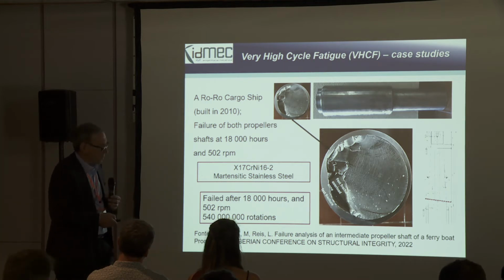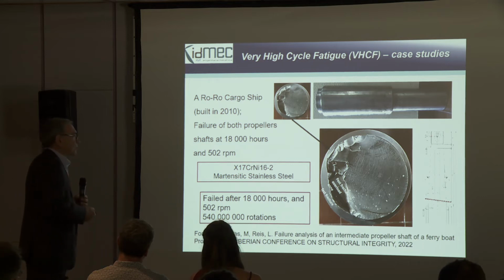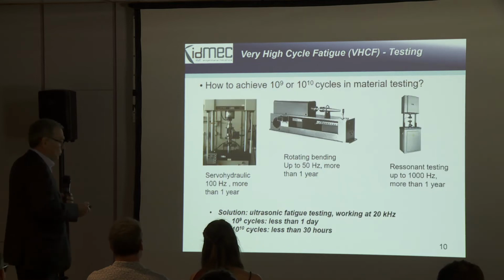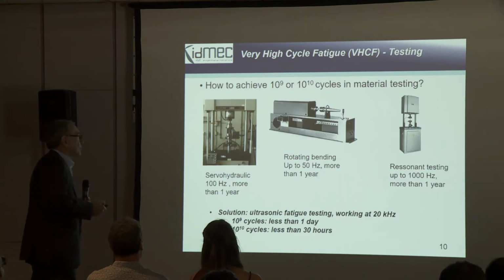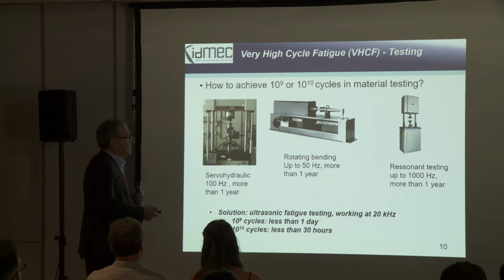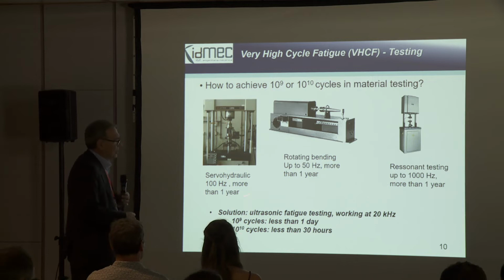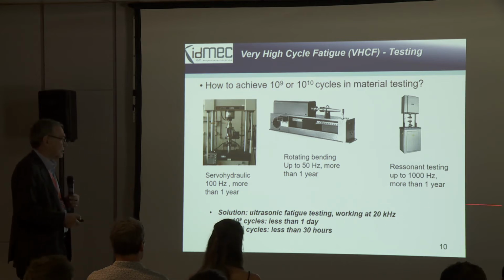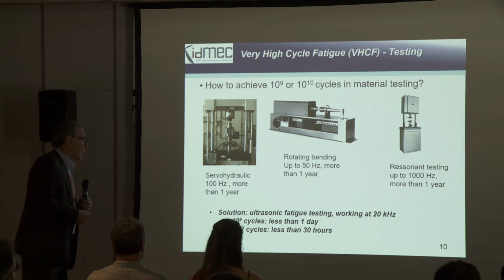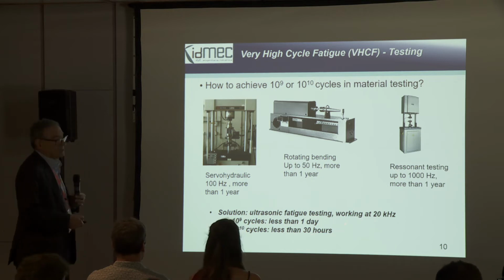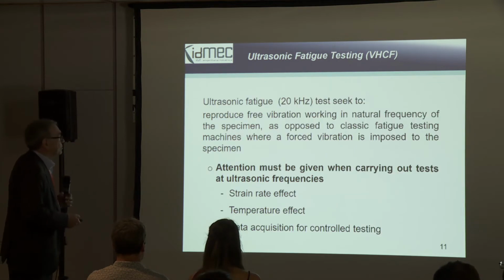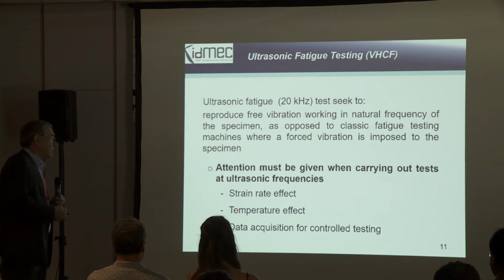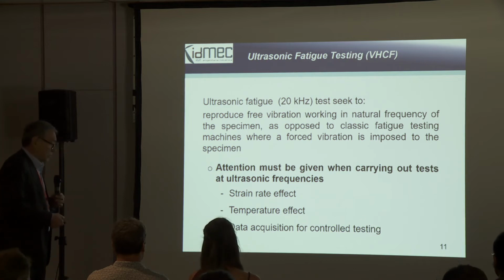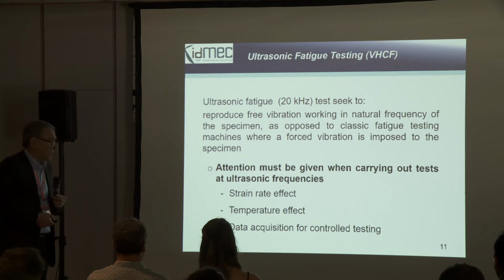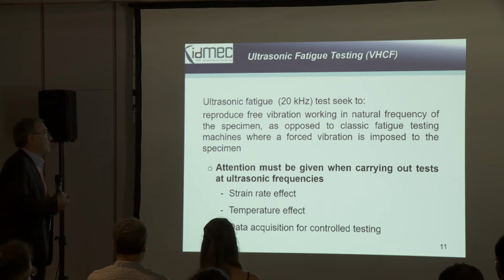So how can we solve that? How can you determine if there is the endurance fatigue limit or there is not the endurance fatigue limit? So the classical way is that one, servo-hydraulic, resonant testing, increasing frequencies, but indeed, we thought that the solution is ultrasonic fatigue testing. We can make 10 power 9 cycles in 1 day or 10 power 10 cycles in less than 30 hours. Of course, we have many problems because we have the strain rate effect, we have the temperature effect, and very important, we must have the data acquisition in order to control the test relating to temperature, loading, frequency, etc.